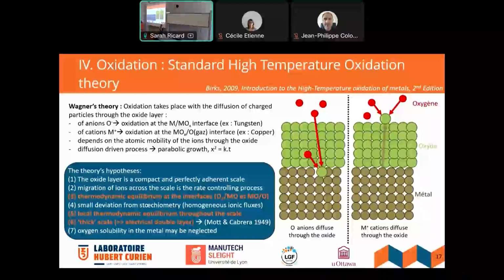There are three main assumptions that may not work under ultrafast laser irradiation. Firstly, thermodynamic equilibrium, either at the interface phases or locally throughout the scale. This one, I think, we can accept. The other one means that, given that oxidation is an exothermic process, we have the time to diffuse heat in the time frame of ultrafast laser excitation, which is uncertain.